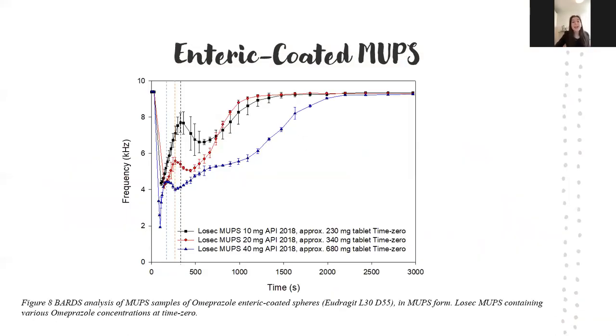So figure 8 represents the data collected for the MUPS formulation of omeprazole, branded Losec MUPS, of 3 different dosages, so 10 milligram, 20 and 40 milligram. The samples were analysed in 0.01 molar NaOH as they're an enteric-coated polymer. And there's actually a 2-event dissolution taking place here. It's very different to ones we've seen previously.